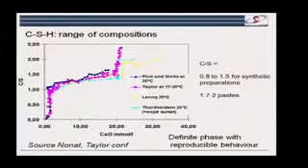So in this graph here, the CSH range is this range here. Okay? At this point here, we also start to form calcium hydroxide, and at this point here, we start to form silica gel. So we produce CSH in cement paste. We can also make it by mixing together different solutions.